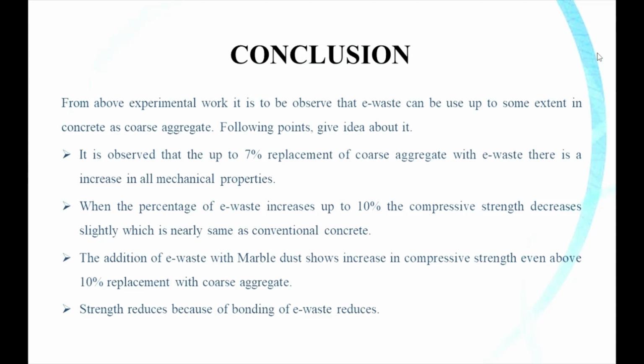The third one is that addition of e-waste with marble dust shows an increase in compressive strength even above 10% replacement of coarse aggregate. So when we add marble dust as an additional material with e-waste, there is an increase in strength compared with the e-waste concrete only. This replacement also works above 10% replacement of coarse aggregate. So marble dust is a good material to increase the strength with e-waste.